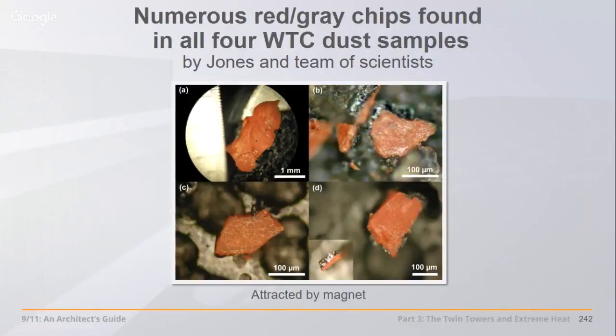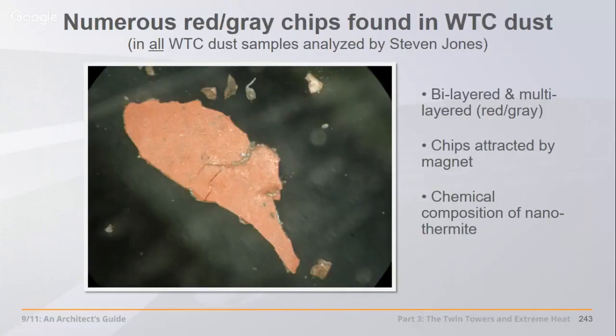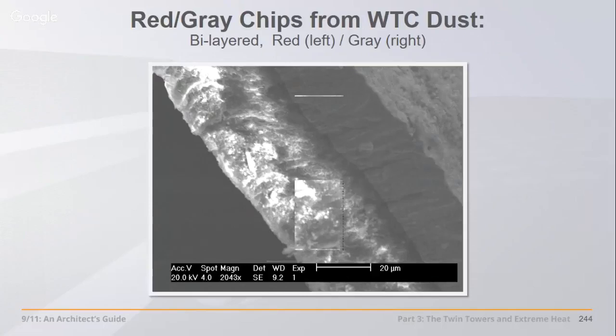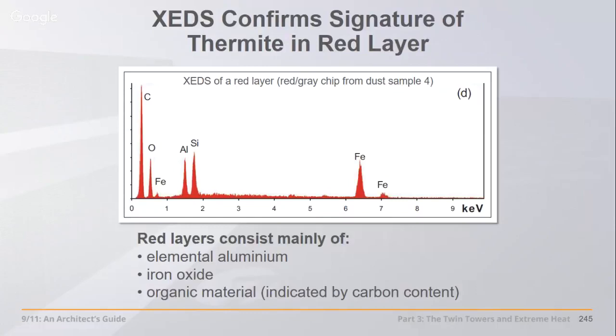But 4 of these samples were analyzed and documented, and they find these chips. They look like paint chips, but they come up to a magnet. They have iron, so they get real curious. They're about a 1/16 of an inch long on average. They zoom into the red side of this, and they find what? Ingredients of aluminum and iron, silica, oxygen, carbon. Wow, what is the ingredients of thermite doing in the World Trade Center dust in all of these red-gray dual-layered chips?